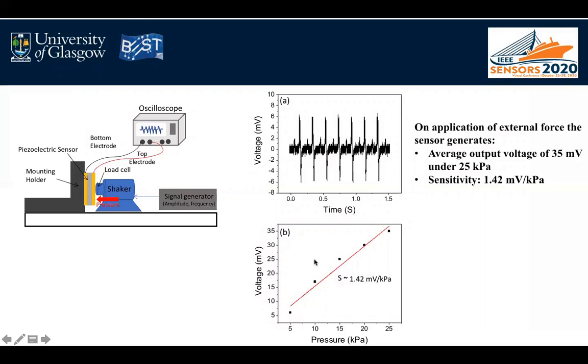And this figure shows that voltage linearly increased with applying compressive pressure, and the sensitivity was about 1.42 millivolt per kilopascal in the pressure range of 5 to 25 kilopascal.